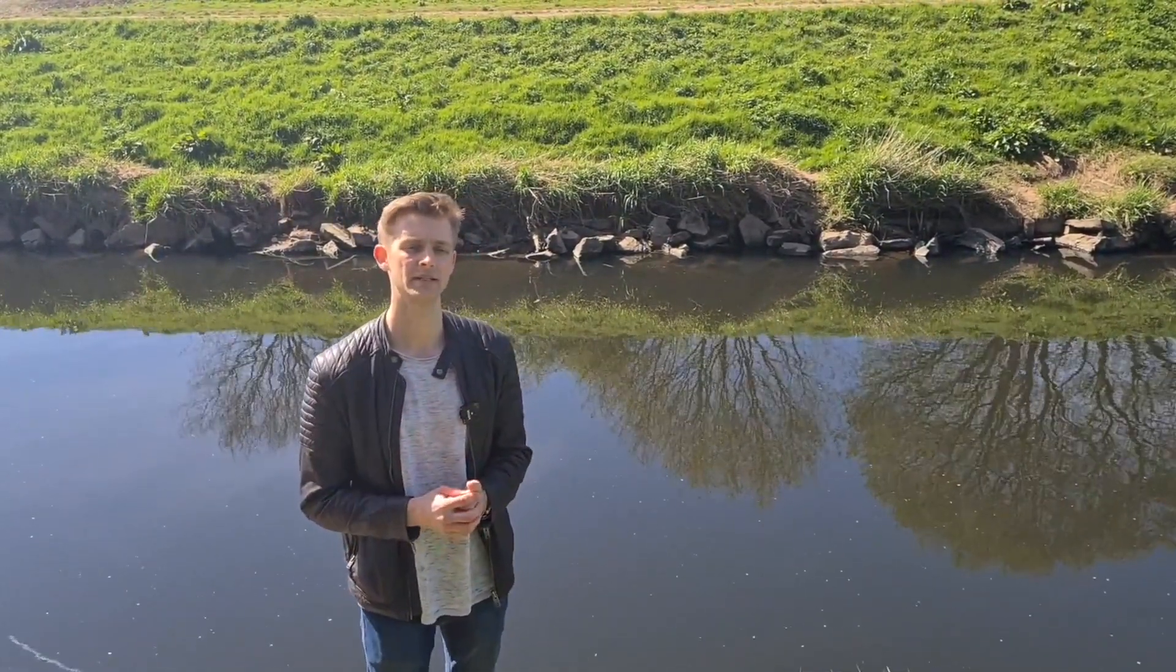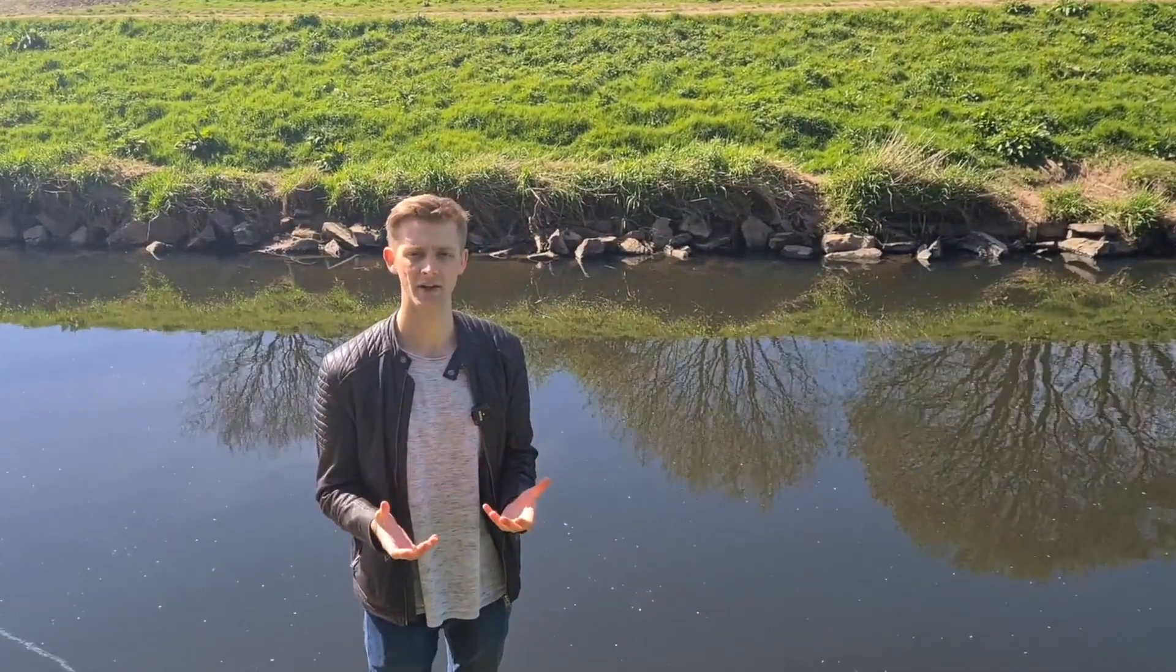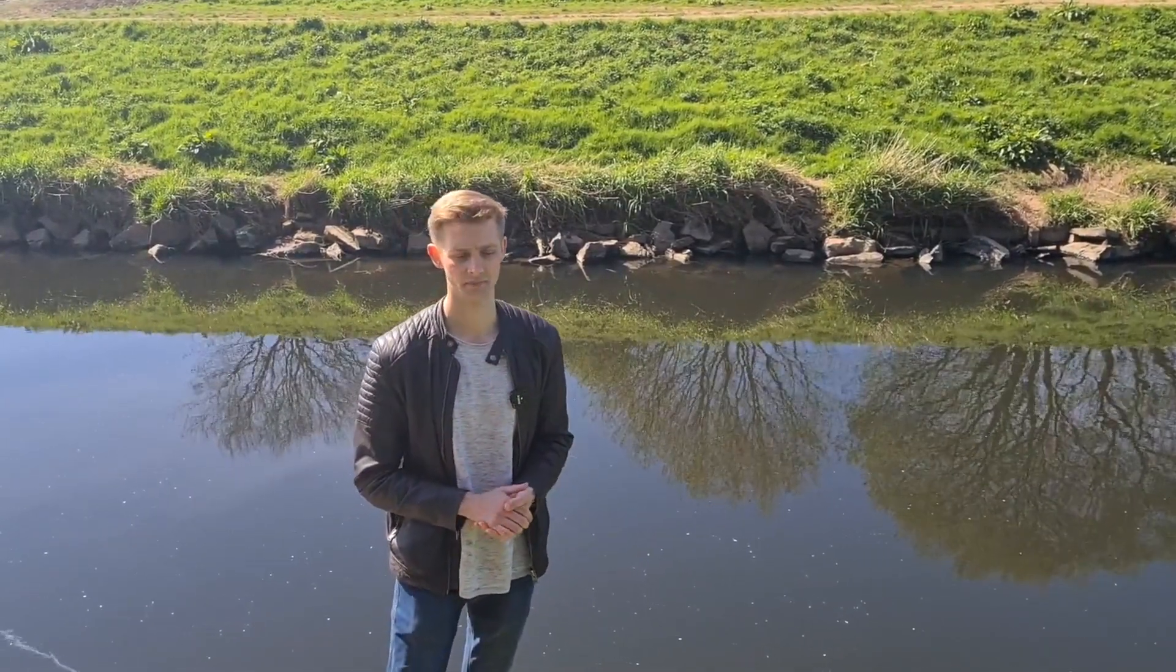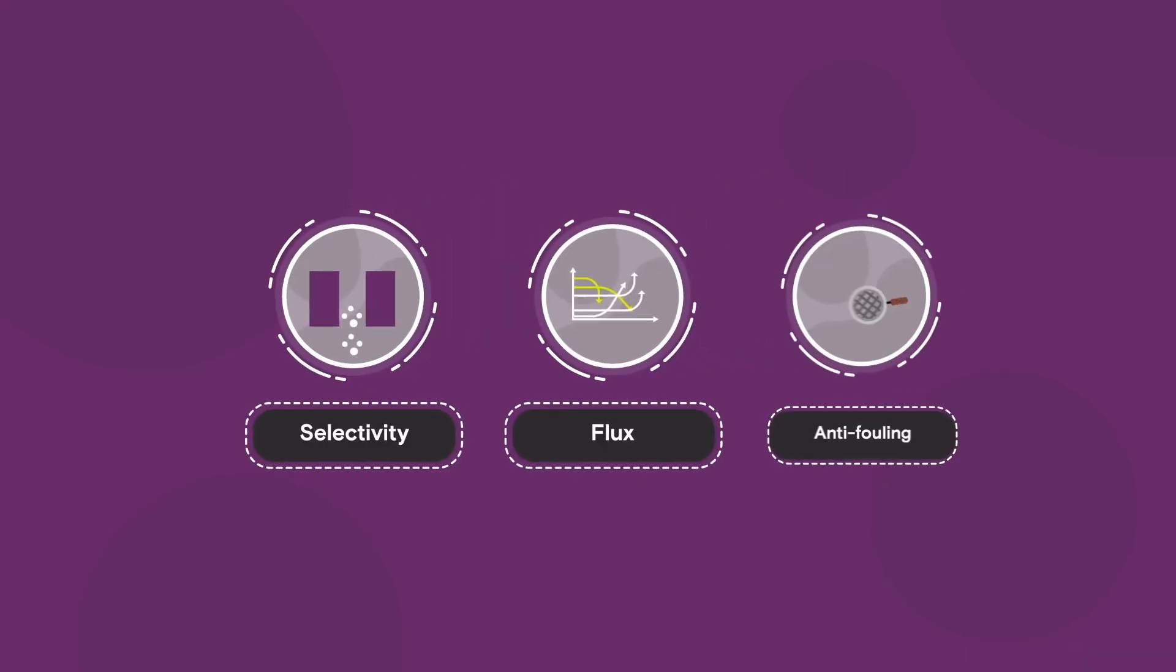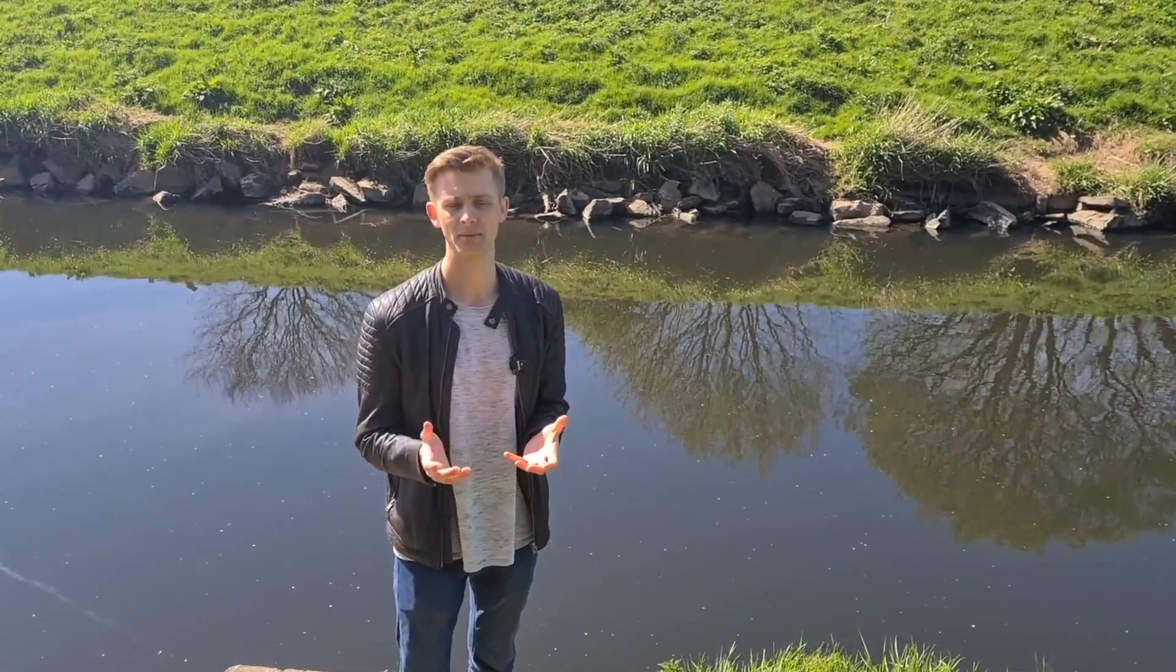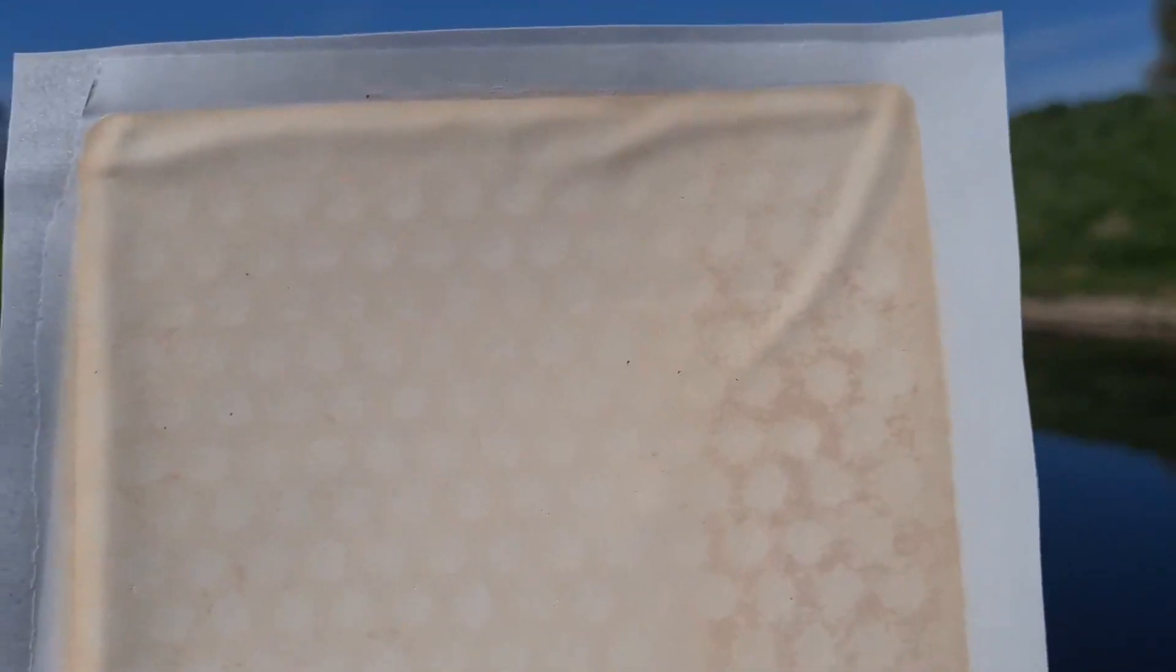If you have a low permeability material, it means that you need more surface area, more membrane area to treat the same amount of water. And this increases your costs. The third most important characteristic is fouling propensity. All membrane processes suffer from fouling. This process is the accumulation of unwanted species that stick and attach to the membrane surface, reducing the flux and potentially affecting the permeability as well.